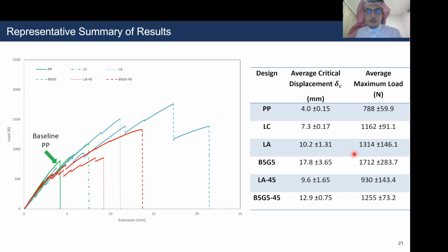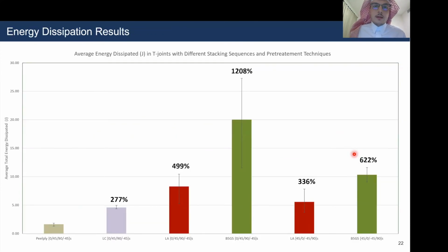So what was the mechanism which resulted in this enhanced toughness? Just before I go to that point, let me illustrate the energy dissipation. The energy dissipation was calculated by finding the area under the load extension curves. And again, similar to the maximum load and the average critical displacement, the energy dissipation was largest with the B5G5. This improvement was recorded as 12 times higher than peel ply. And when the fibers were switched to 45 degrees, it was only 6 times higher than peel ply. So the energy dissipated, as I said, the area under the curve almost doubled when moving from 45 to 0.